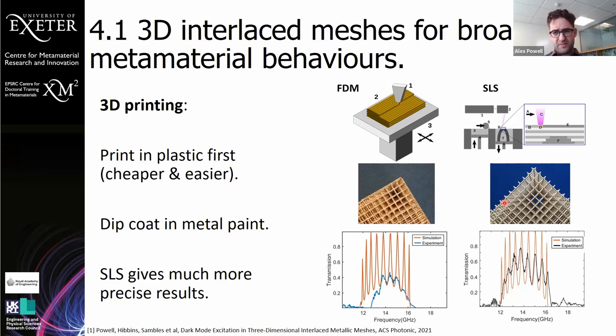We did try electroplating, but it's kind of difficult with these mesh structures because you do get quite a lot of shielding. So electroplating is not always as easy to coat in the center as the outside, which is a subject for future experimental investigation. But this is a much better result. We can see about double the transmission, and we can see the whole transmission window, which is what we'd predict for these structures.